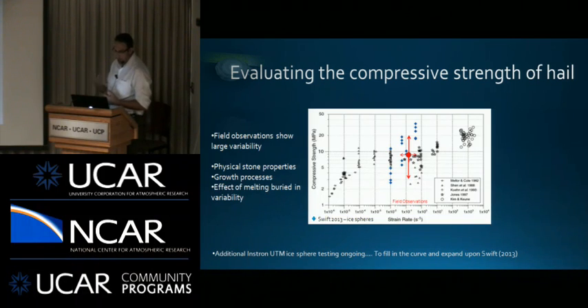So if you looked at the effect of melting, and we collect stones after they've fallen, there's so much variability in there, it's hard to even extract where that comes from. So you could pick up a stone that might have been on the ground for 15 minutes and it'd be extraordinarily hard, or you could be right behind it, and the thing's only been there for 5 minutes or so, and it's just slush. It's hard to back that out.